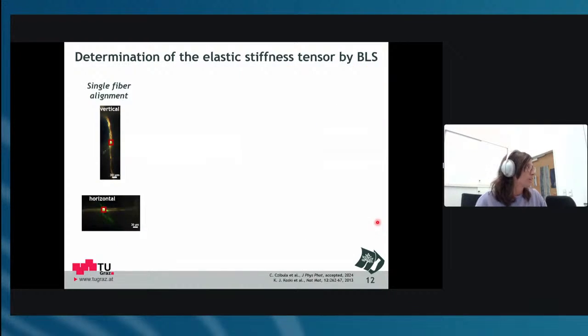Yeah. And now I will guide you through this determination of the elastic stiffness tensor. So you see now I can mount the fiber horizontally and vertically, and I can go between that. I mostly started out horizontally, and then I turned it until 90 degrees, and in between always did some measurements. But basically we have all the freedom in this setup, so we can turn it all the way and also around itself. There are no limits there.